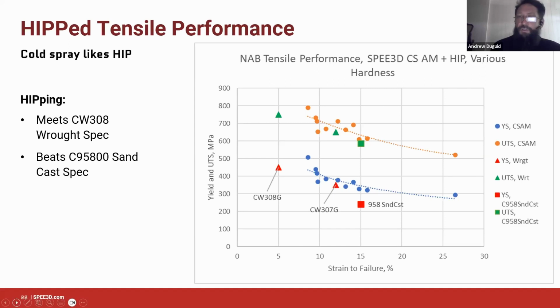What we didn't look for is that when we inadvertently moved the conditions up to a higher hardness value, we're actually not looking too bad against the wrought spec either. It's a little bit touch and go. But if we do a statistical study on that, we'd find that we were basically meeting the wrought spec as well with that HIPping process, and that's great. That's sort of a holy grail. Metallurgists are pessimists, right? So I run around telling people, no, we are not going to meet the wrought spec. And it's always lovely being proved wrong when we do it anyway. Okay, so we'll go on to the next slide.